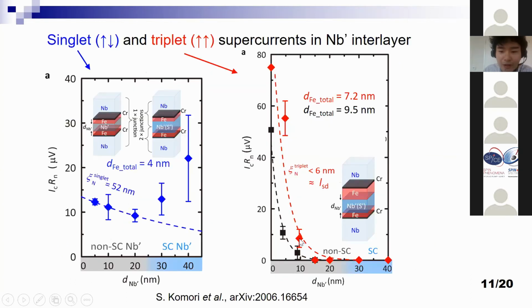So this is the experimental results. We have devices with thin iron layers and thick iron layers. This left figure shows the trend for singlet supercurrent as a function of niobium interlayer thickness, and this right one is the trend for triplet. I would like to explain from this left figure. We deposited many samples with different niobium interlayer thickness. And here niobium has two regions, a non-superconducting region and a superconducting region.